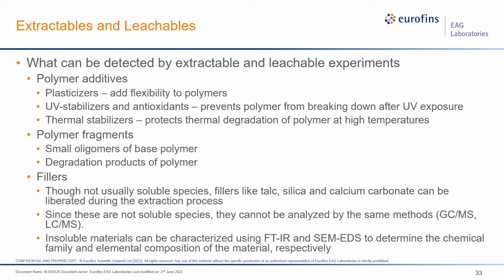And depending on how the sample swells, we may be able to detect any sort of other inorganic fillers. So these may be left at the bottom of the extraction vessel for inorganics like talc, silica, or calcium carbonate. Since these are not soluble species, we're going to have to use some different techniques to analyze them, and we'll use our old friends FTIR and EDS to determine their chemical family and elemental composition respectively.